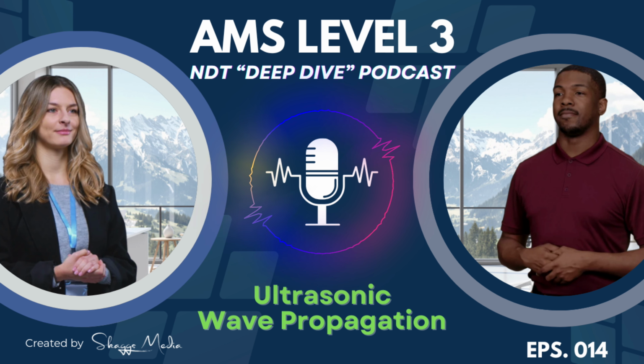Because there was one reflection case you mentioned earlier that sounded much simpler. Absolutely. The simplest reflection scenario involves what's called a transverse horizontal wave, or SH wave. In this case, the particle vibrations are still transverse, perpendicular to propagation, but they are oriented parallel to the reflecting surface, horizontally. When an SH wave hits a stress-free boundary, it reflects only as another SH wave. The reflected amplitude equals the incident amplitude, and crucially, no mode conversion occurs. No longitudinal wave is generated. It's the cleanest, simplest reflection possible in solids.